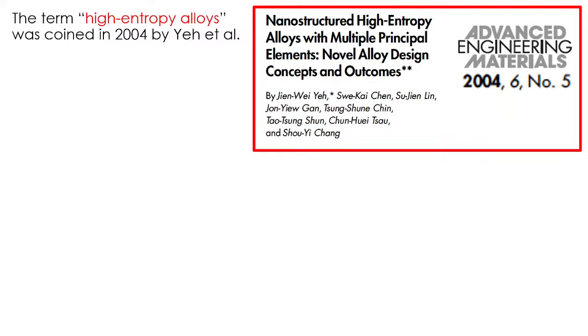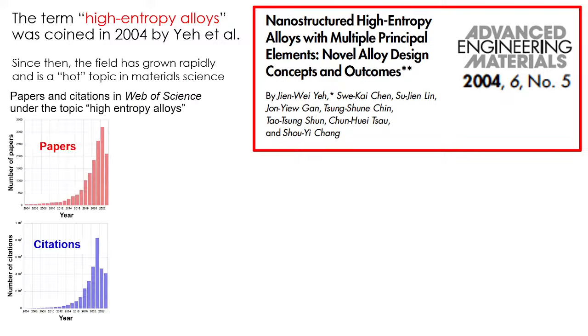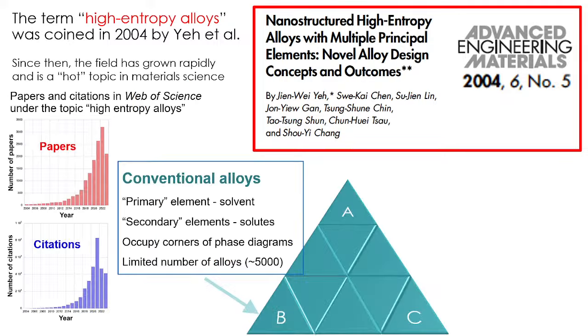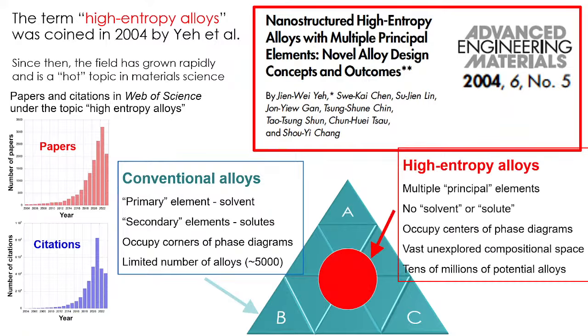So just to put things in perspective, in a conventional alloy, you have a primary solvent. If you have an aluminum alloy, aluminum is the solvent, and then you add secondary elements like silicon to it. And they occupy the corners of the phase diagram. So this is the ternary phase diagram. These conventional alloys are in this corner. High entropy alloys are in the middle of the phase diagram. So there's no solvent or solute in the conventional sense. There are multiple principal elements, and there's a vastly greater number of these alloys, in the tens of millions rather than a few thousand in the corners, by the nature of the combinations that you can get. So a lot of this is unexplored.